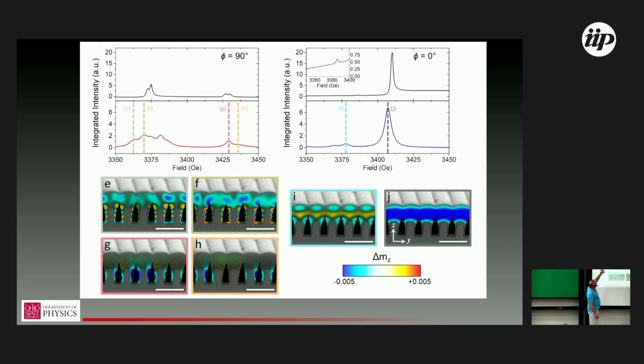So the amplitudes don't directly correlate, and the fields aren't quite exact. The amplitude variation is just because the mumax calculation doesn't have any detection physics in it. Right? We have to couple to our cavity, and that has some symmetries and sensitivities that mean we don't see all spin waves equally. And the small field shift, like say in the E and F lines on the left to the data, in the business of modeling magnetization dynamics, that's bang on. That's just within a few Gauss. And the really powerful thing that the mumax simulation can do for us, similar to the disks that I showed a moment ago, is you can sort of map the phase of the magnetization throughout the magnetic structure.